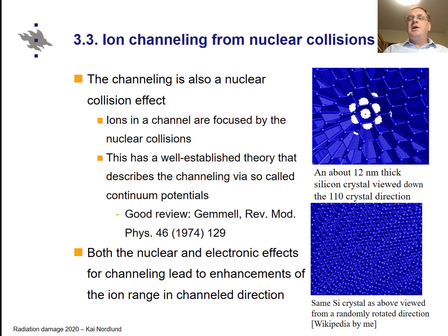So it's fairly easy to understand that an ion traveling in this direction could get further than if it travels in this direction perpendicular to this thing. Well, actually, it's more complicated than that, and the effect is even stronger because there is a focusing effect. There is an analytical theory starting from Lindhard, which describes this focusing effect with so-called continuum potentials. This means that due to the focusing, if an ion happens to come into one of these channels, then the atoms tend to keep it focused so that it's actually difficult for the ion to leave the channel, and this strengthens further this channeling effect.